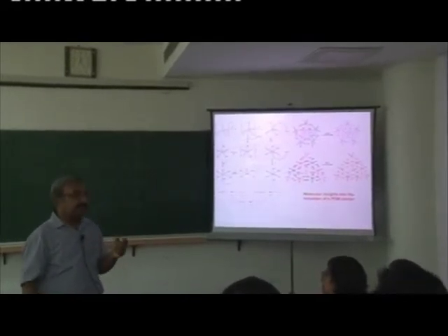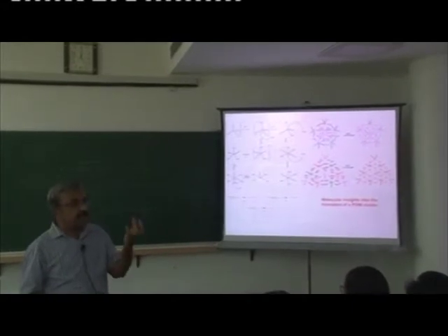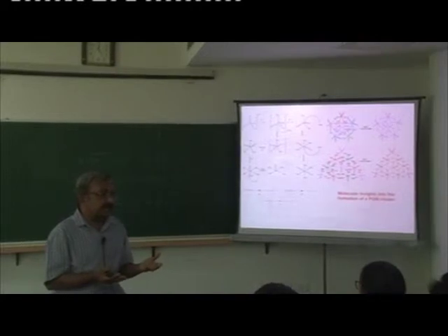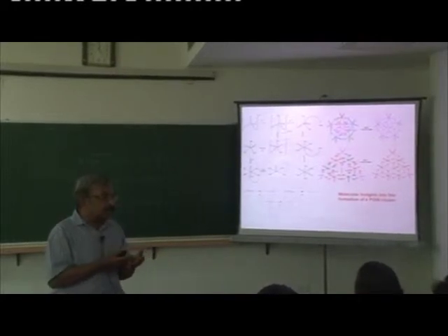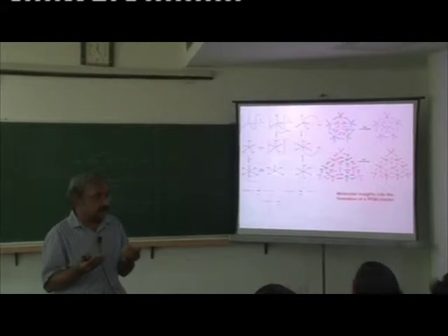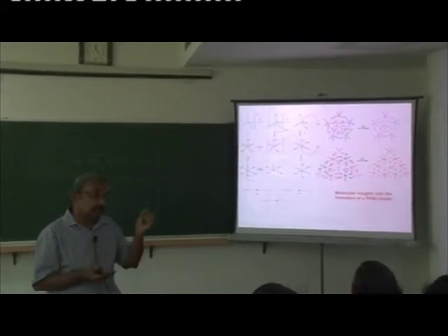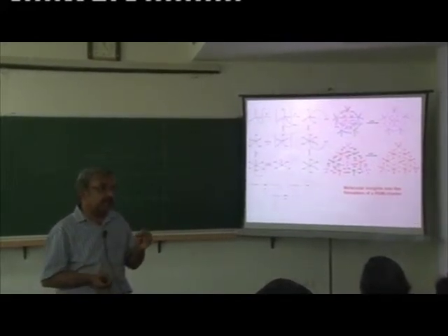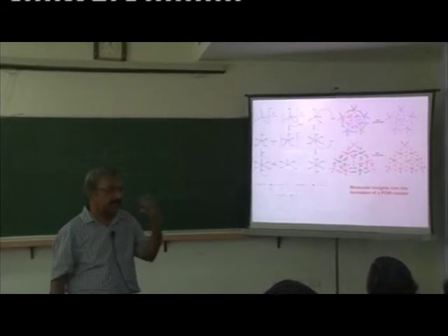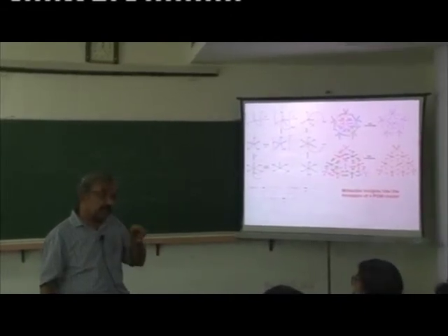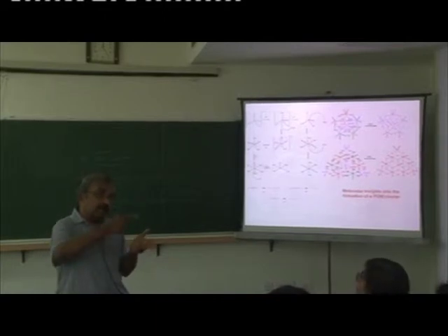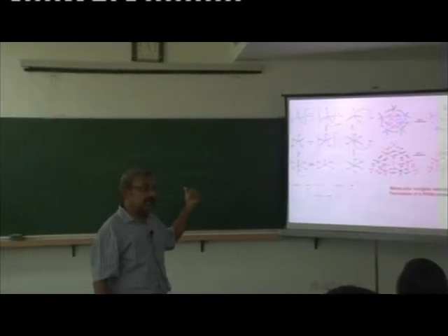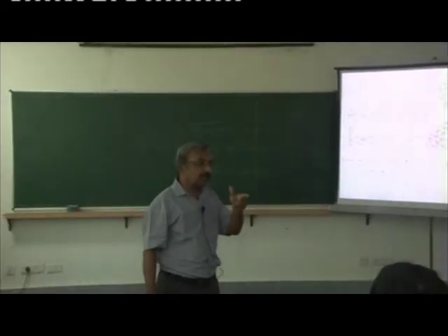In the case of copper sulfate itself, because of the nature of the metal ion itself, because it is acidic, right? And it is competing with the water. That hydrolysis is going to vary. So the moment you disturb it, as I told you already, by adding a little bit of ammonia or hydroxide or whatever it is, then the pH is going to change. It's not necessary you have to come to pH 7 or greater to have those hydroxy sulfate phases. You follow what I am talking about?